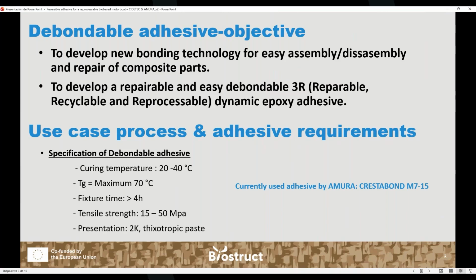Regarding the curing temperature, it needs to cure at room temperature or at maximum 40 degrees. It needs to have a Tg around 70 degrees. We need a fixture time around 4 hours. Regarding the tensile strength, it's quite open, between 15 and 50 megapascals. And regarding the presentation, we need a two-component epoxy adhesive, thixotropic paste.